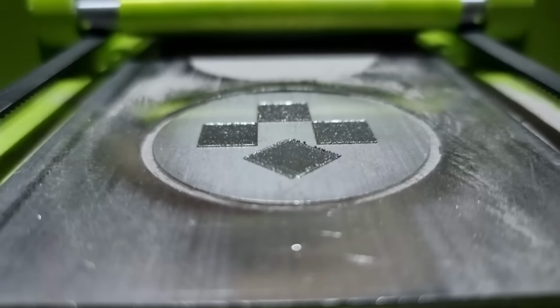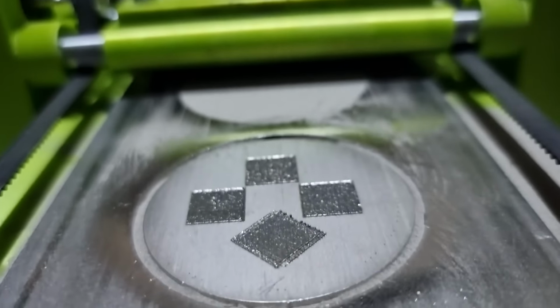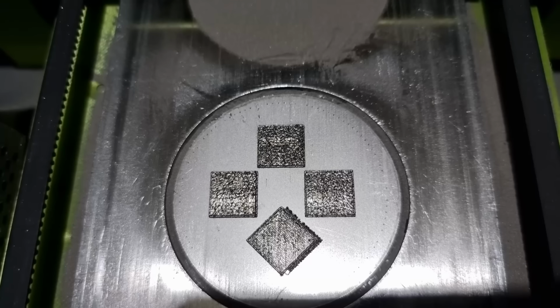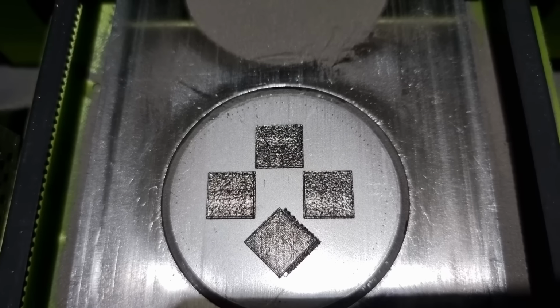At 25 micrometers, the irregularities remained but in a different format, seeming to embed the spatter from the previously processed tracks. I decided to push ahead and start stacking layers as the consequences of each spacing wouldn't really be known until given a chance to materialize. I only managed around half a dozen layers as the build piston would break free, but still managed to observe the settling of each scan pattern.